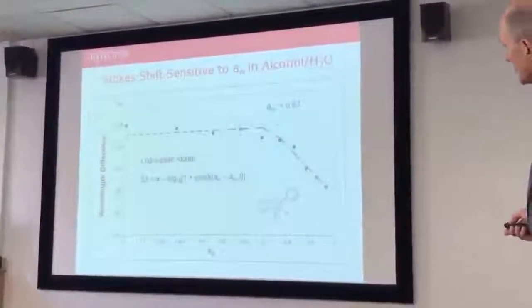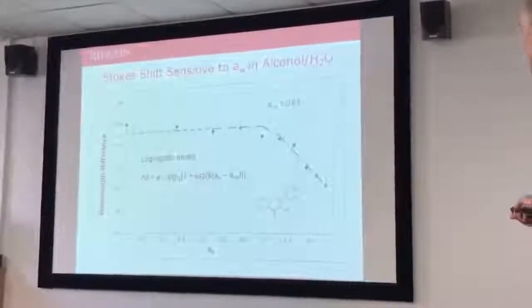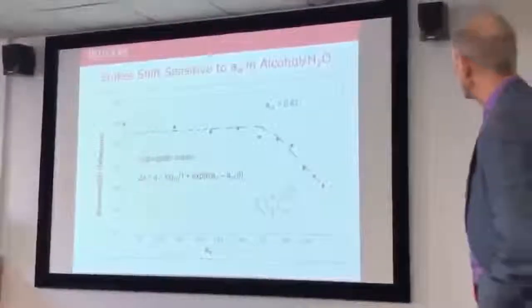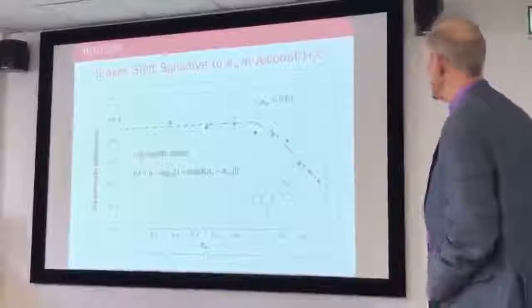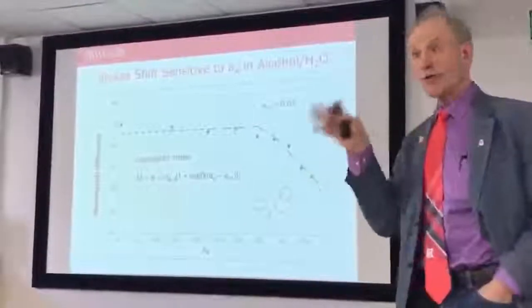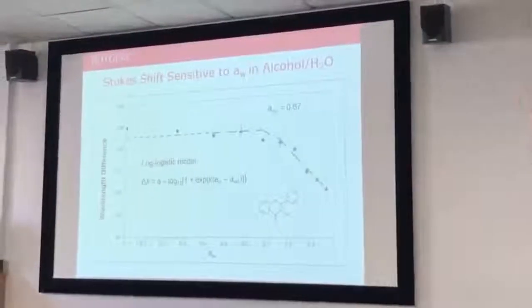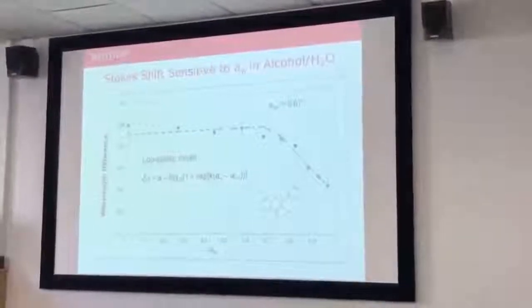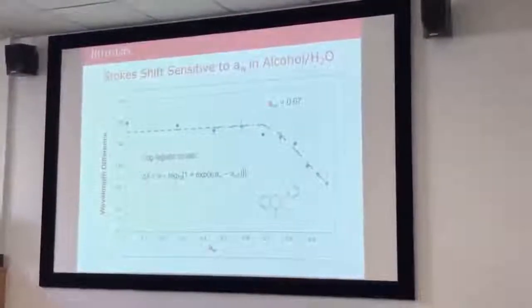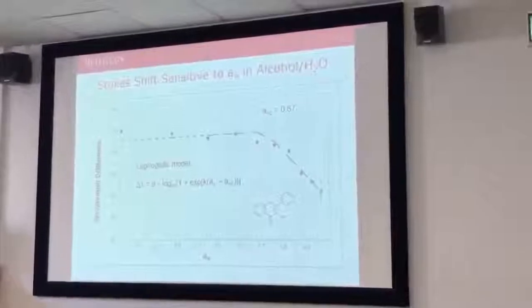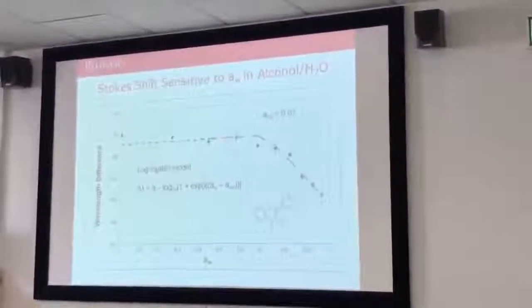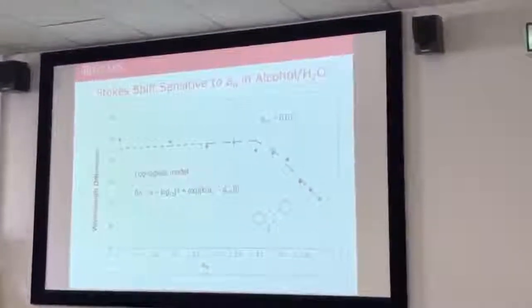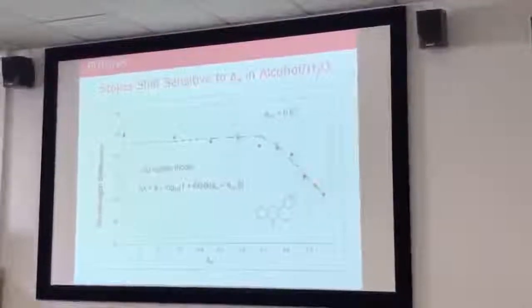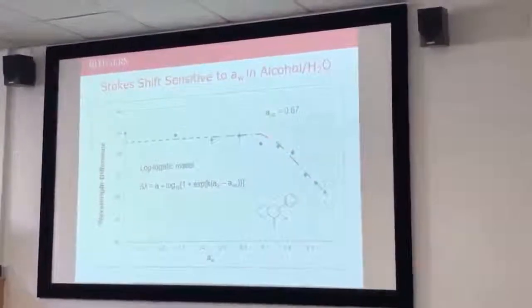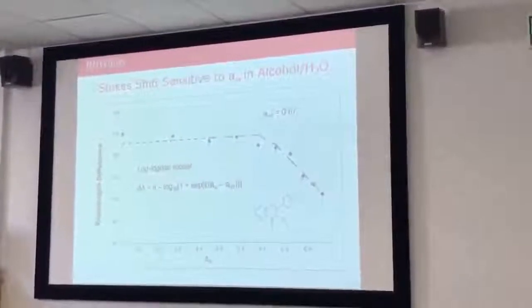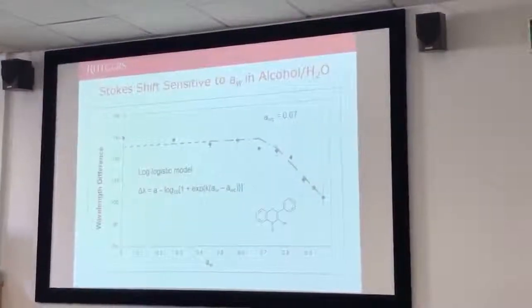And if you plot the Stokes shift, the wavelength difference, versus a_w, this is in alcohol water. This particular one is ethanol, and we've done methanol as well. So in ethanol and methanol, we have a water activity probe. In this case of hydroxyflavone, we've got a probe which is essentially immune to the water activity up to about 0.7, and then it shifts. So this probe is sensitive to the water activity between about 0.7 and 1. Well, that's kind of a nice range.